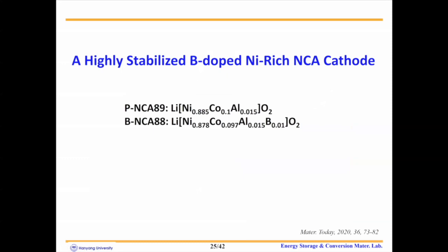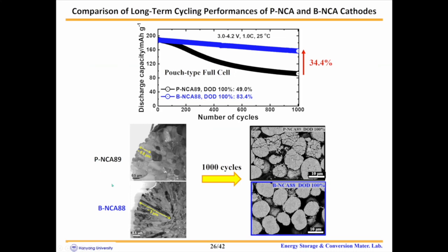And let me show our typical example. First, we developed boron-doped nickel-rich NCA cathode. We prepared two cathodes. One is pristine NCA, the other is 1 mole% boron-doped NCA called BNCA. As shown in these figures, the microstructure of the BNCA cathode material notably changed to have long rod-shaped primary particles with a length of 3 micrometers. Accordingly, the BNCA cathode shows much improved cycling stability with a capacity retention of 83% after 1,000 cycles.